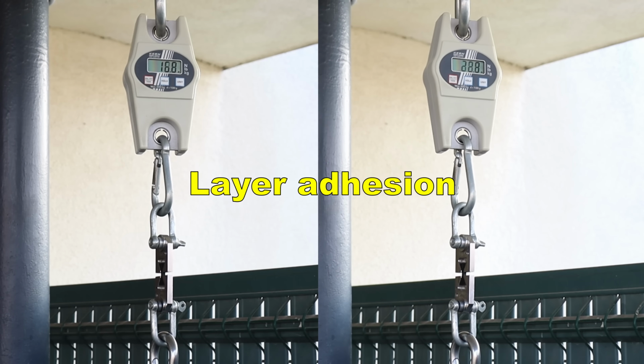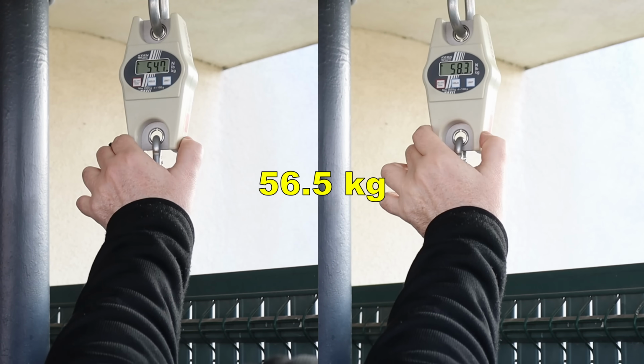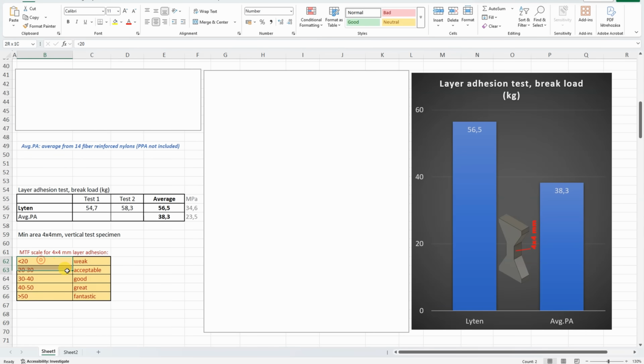Layer adhesion, vertically printed test specimens. Layer adhesion, this is my table with the rating for this size of the test object, and we can see according to this the Lyten has fantastic layer adhesion, much better compared to the average PA. By the way, I got a few comments on why I'm using kilograms for the comparison. Megapascals are always here, or Newtons per square millimeter, but I think it's a little bit easier for a non-technical person to imagine that, let's say, we have a 4x4 millimeter test object and it breaks under 50 kilograms, for example. But the numbers in megapascals are always here.